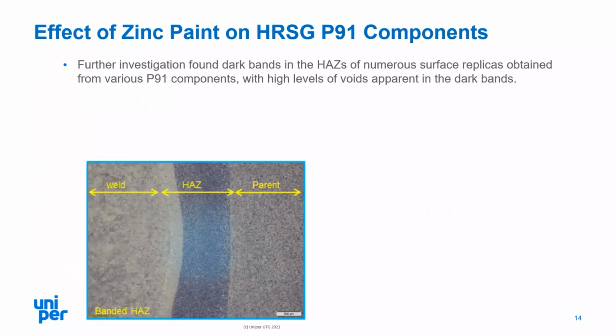Back to where we started with the steam vessel on which the dark band had been identified. Investigation continued. Colleagues at the Technology Centre at Ratcliffe found dark bands in the heat affected zones of numerous surface replicas from several P91 components. And once again, they found high levels of voids in the dark bands which had been seen there.